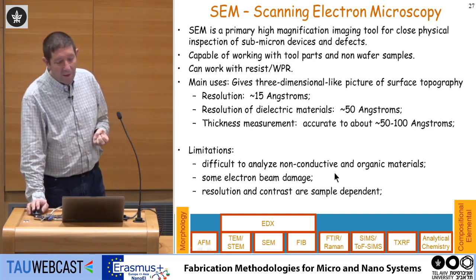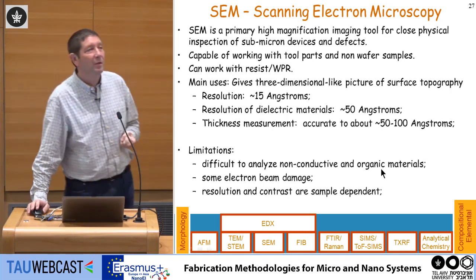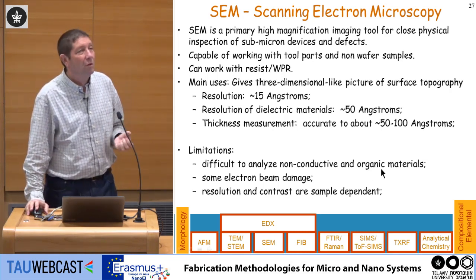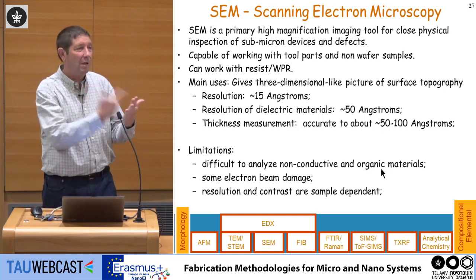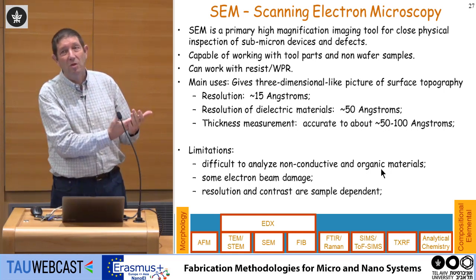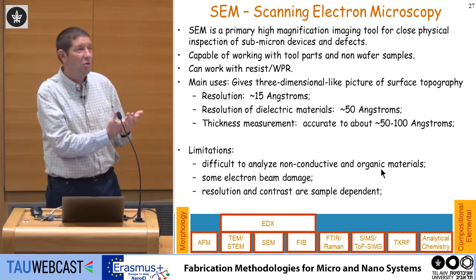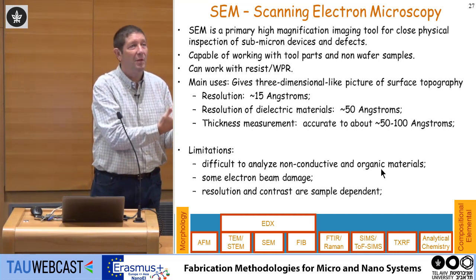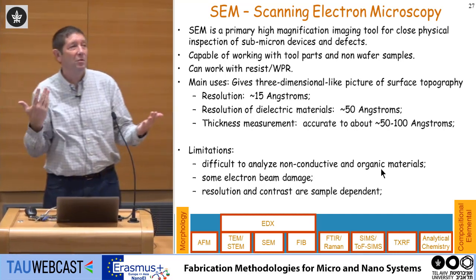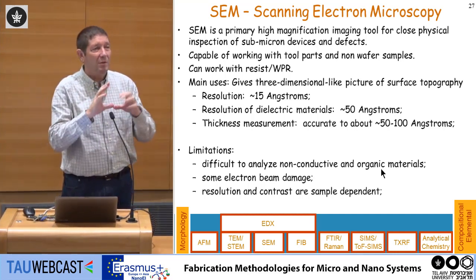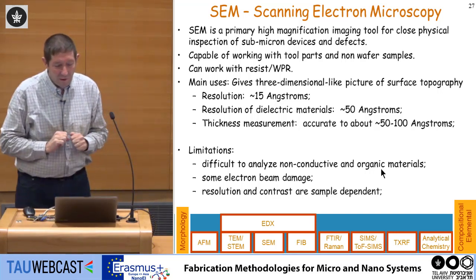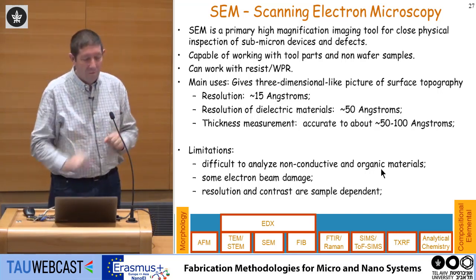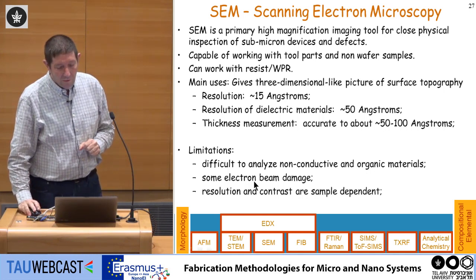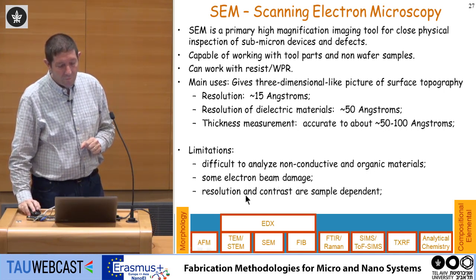It's difficult to analyze non-conducting and organic materials because they are non-conducting. So when you shoot electrons on a non-conducting material, we can charge it. If we charge it, suddenly the surface becomes negatively charged and it repels the electrons, so the image will start to become dark and fade. There is some electron beam damage, and resolution and contrast are sample dependent.